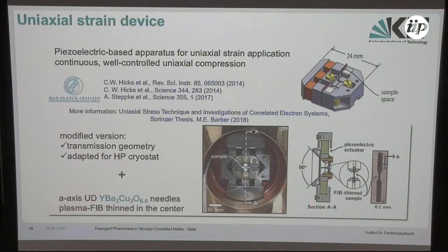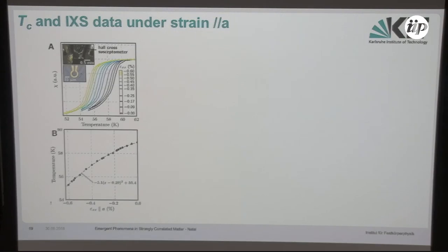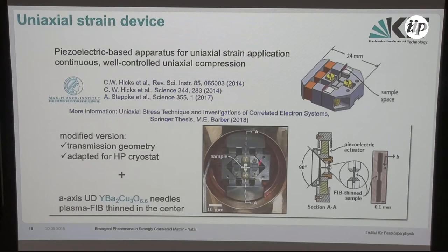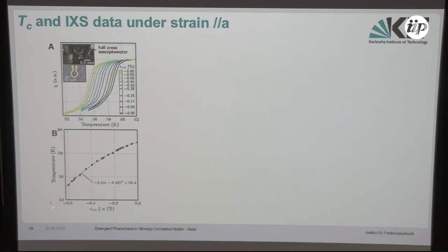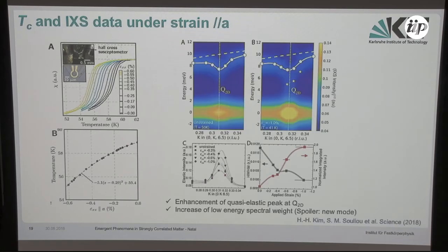So we made this basically pressure cell with a sample in the center of rotation, and then we could make a needle and start doing inelastic X-ray scattering. So we could check that indeed when we apply pressure along the A-axis, now we suppress superconductivity, which is what we wanted to do. And now we start looking at what we do to our charge density wave.